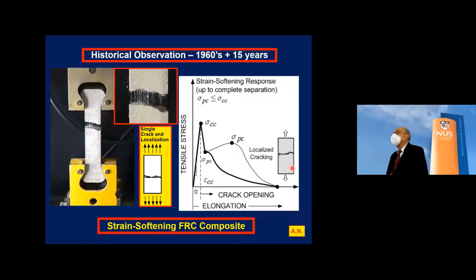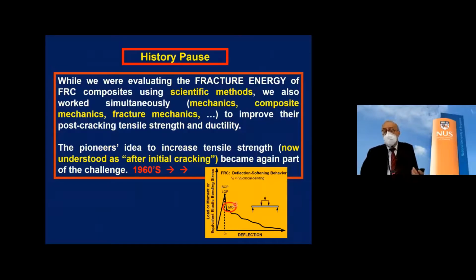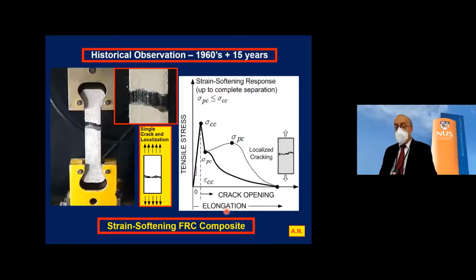Now, today, when I want to characterize fiber reinforced concrete in general from a performance viewpoint, I can say it is strain softening or strain hardening. Now, strain softening is a little bit like this curve here. This is deflection softening, but in a way, after cracking, the load drops and it never picks up more than the cracking load. So I show here today a definition of strain softening response, which is you reach the point at which you have a crack, the load drops, maybe it increases this way or this way, but in any case, always the maximum post-cracking stress is less than the cracking stress.